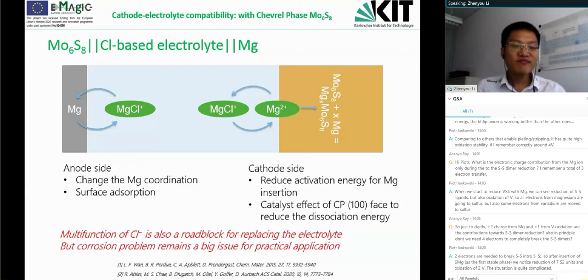So there's no doubt that the combination between the Chevrel phase with chlorine-based electrolyte is successful, but the multifunction of chlorine also makes it difficult if we want to replace it with a chlorine-free electrolyte system. But the case is that we tried it, and the compatibility between our borate electrolyte and the Chevrel phase is quite good. So as shown in the charge and discharge curve here, we have a nice plateau and also a good capacity and low overpotentials after the first few cycles.